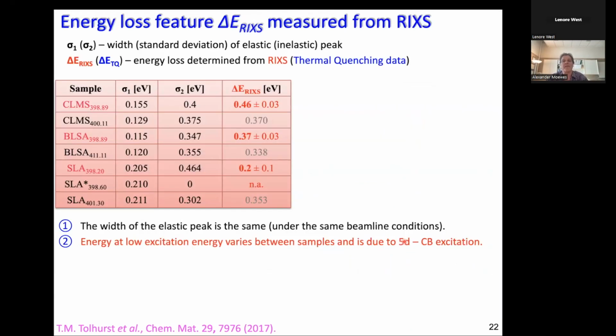So the first thing is we assigned this first intuitively, we assigned this process due to the loss feature due to europium. What is the process? So then what we did, so what you see here, the sigma only fitting parameters. So you see here for the 3 different samples in red, the 3 energy loss features for different host lattices. Again, we have different energy losses of 0.2, 0.37, and 0.46. These are the loss features, the energy losses in our resonant inelastic X-ray scattering spectra.